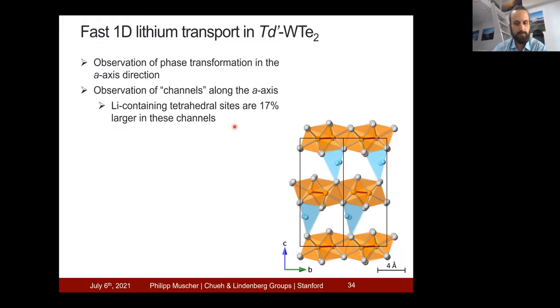And looking at the atomic structure of TD prime tungsten ditelluride, we can actually see that there are channels in this van der Waals gap in which the lithium ions are sitting. And in these channels, the tetrahedral sites in which the lithium is sitting are actually 17% larger than the tetrahedral sites outside of these channels.